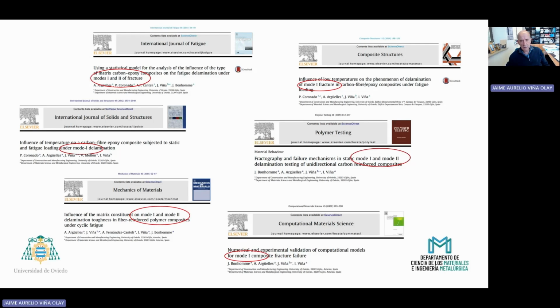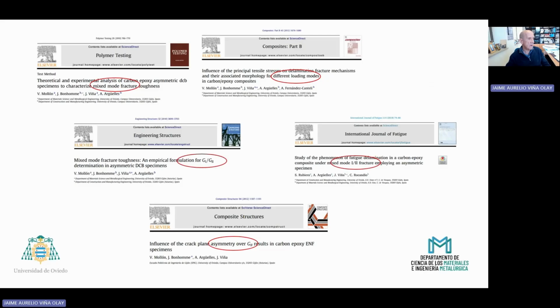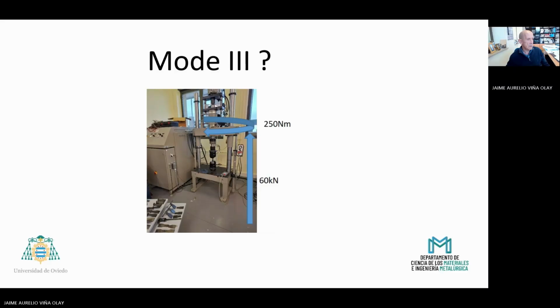Here we present some of our papers in the field of fracture composite in mode 1 and mode 2, both static and dynamic. And here we have the same static and dynamic, but in mixed mode 1, 2. At this point, we decide to explore mode 3 testing. But when we review the literature, we found that the usual test was not very satisfactory for us. Why? Because the static test in mode 3 was our first objective, but we want to carry out testing, dynamic test in mode 3 also.